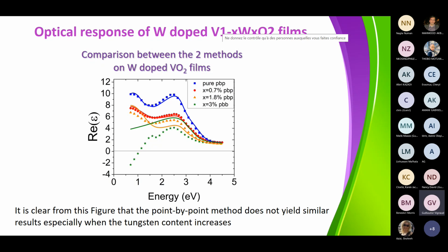And typically, you can see that with the point-by-point method, the real part of epsilon becomes negative here, meaning that at 3% at room temperature, there is a metallic component in your material. And you believe that you are in an insulating phase, because normally the transition was found around 40 degrees Celsius. So if you are at 25, you would say, oh, I'm safe, I've gone through the transition, this is now an insulating phase. But the ellipsometry is telling you that this is not the case. And diffraction is also telling you that. I didn't comment on it, but actually you never reach a full percentage of the monoclinic phase.